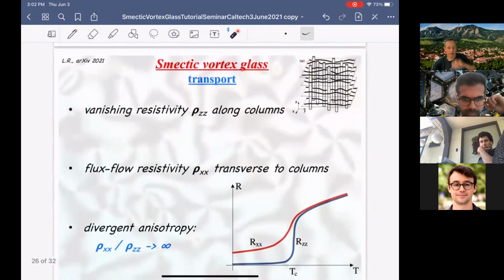Finally, the most striking thing is the transport. Let me just first state it. Imagine I run current in the z direction along the columnar defects. When I do that, that creates a Magnus force perpendicular to columns. So there's a force on vortices that pushes them in this direction across the columns. Because they're pinned by the cross sections of the columns, they cannot move, and therefore you have a vanishing resistivity. So for current along this direction, there's no voltage.